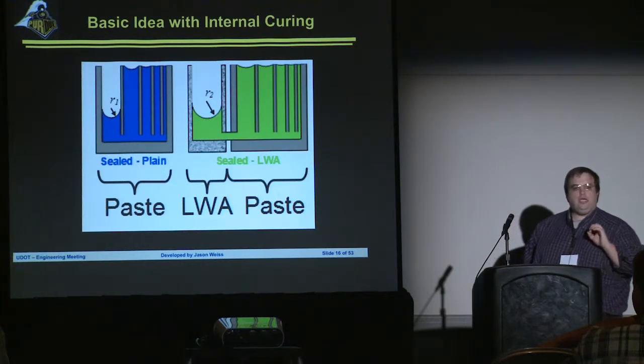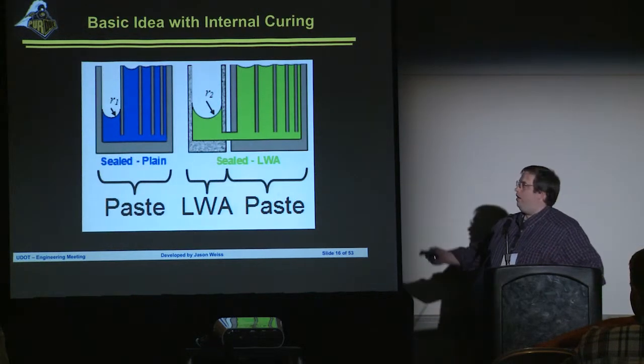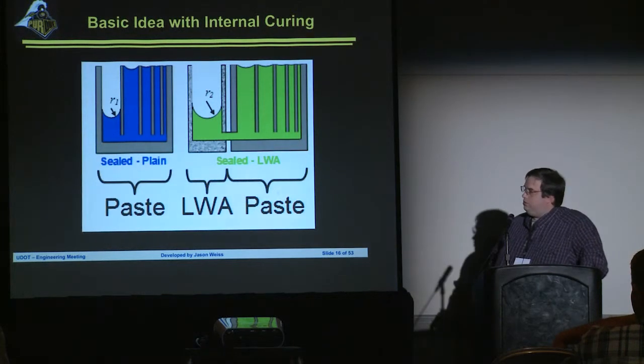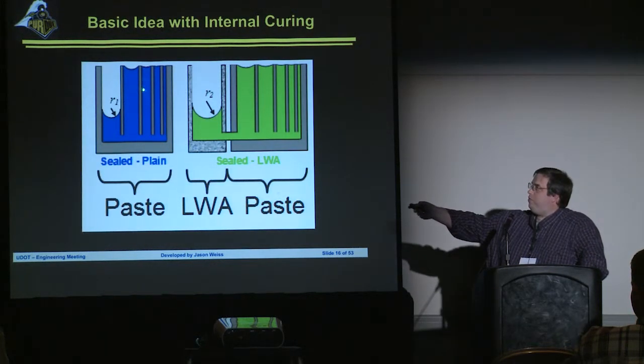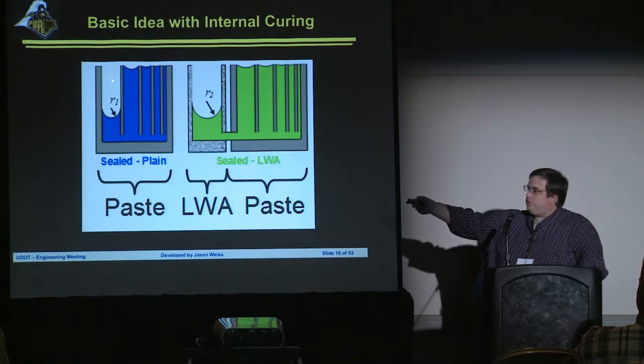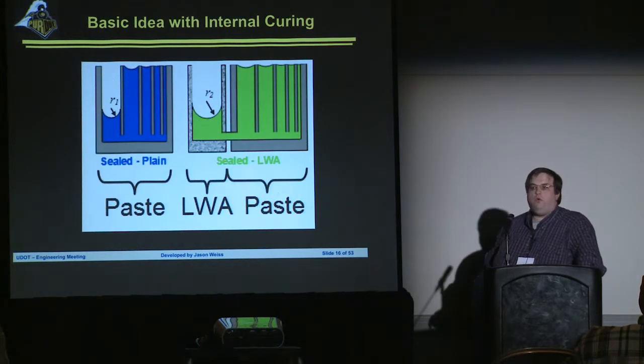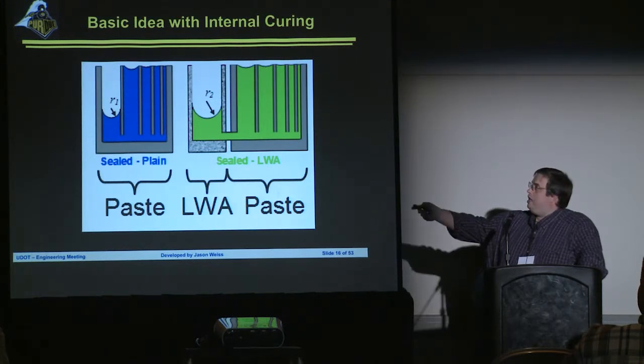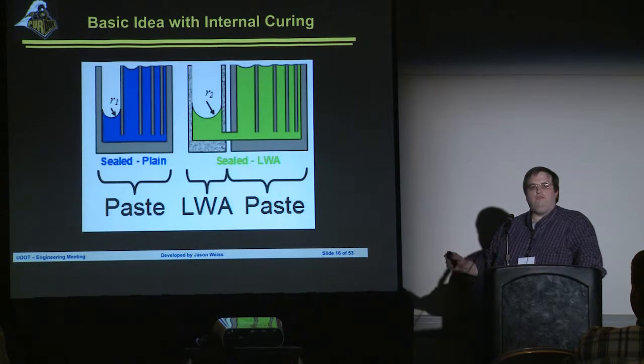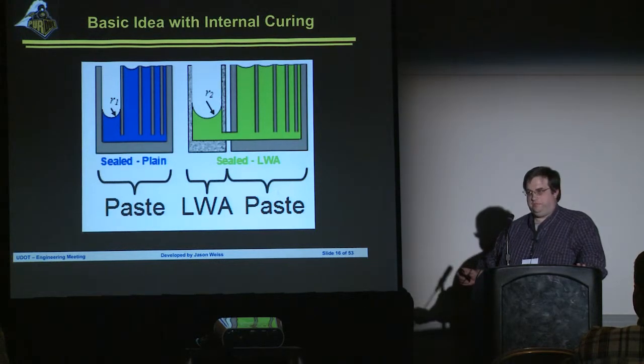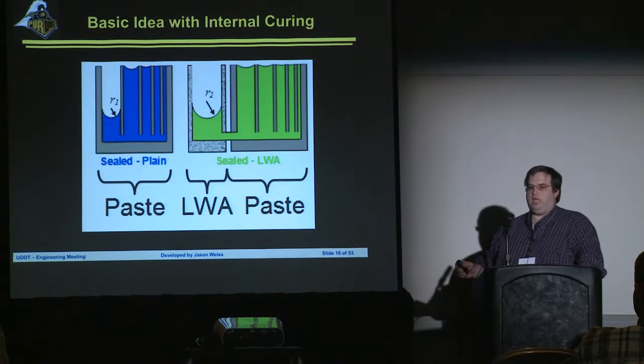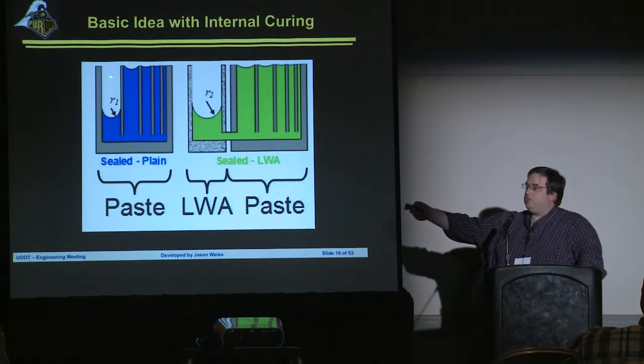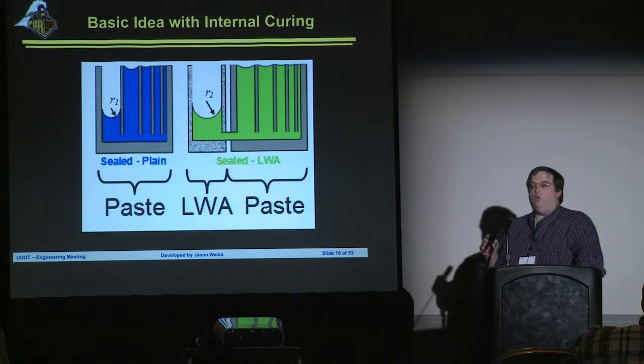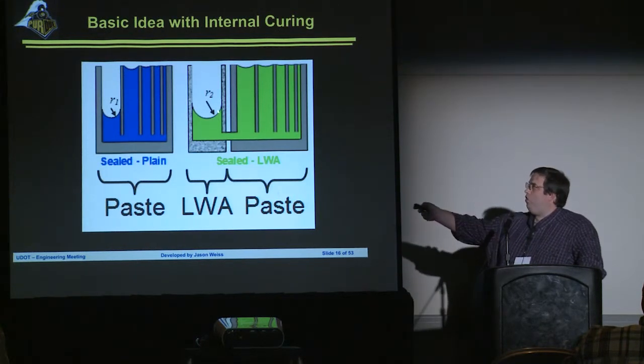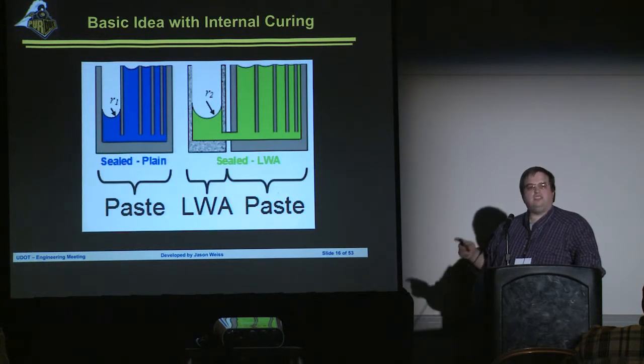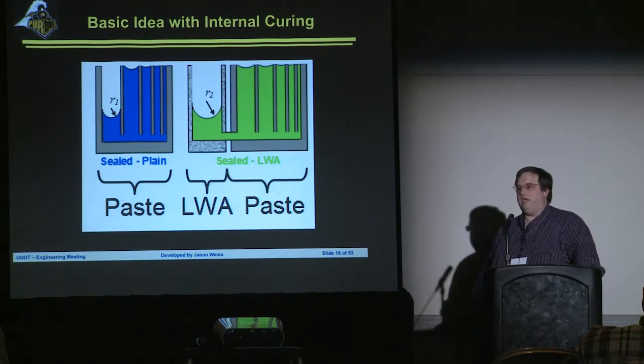All right? The whole premise to which this works on, again my horrendous cartoon skills over here, is that we have different sized pores inside of our concrete. We've got big pores, we're going to call them capillary pores. We've got small pores that we can call gel pores. All right? The basic premise of all of physics is big pores empty first. It's lower energy for the big pores to empty. What we're doing with internal curing is we're hiding water inside of lightweight aggregate that's a slightly bigger pore than we have inside of our paste.